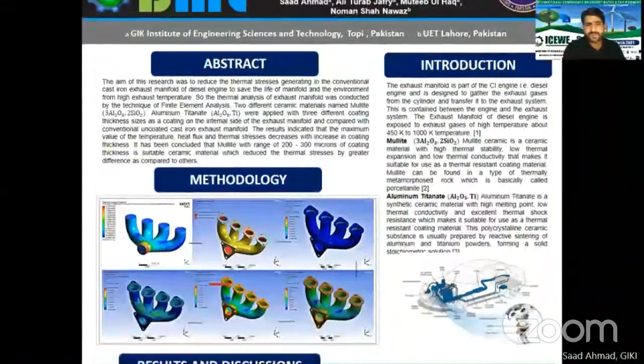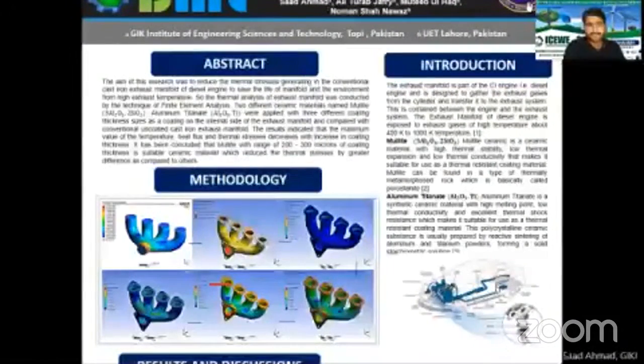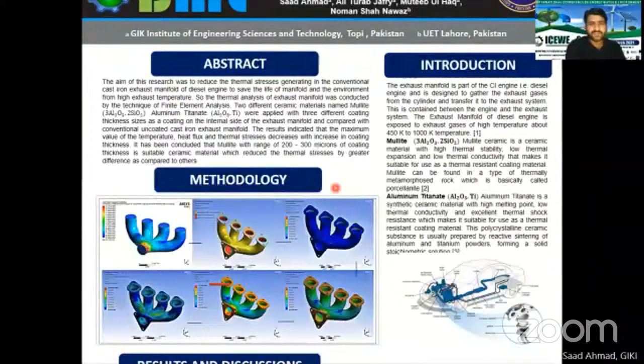The aim of this research was to reduce the thermal stresses generated in the conventional cast iron exhaust manifold of a diesel engine, to save the life of the manifold and the environment from high exhaust gas temperature. For this, two ceramic materials, aluminum titanate and mullite, were applied as an internal coating of the exhaust manifold with coating thicknesses of 200, 300, and 400 microns, and three different analyses were then conducted.